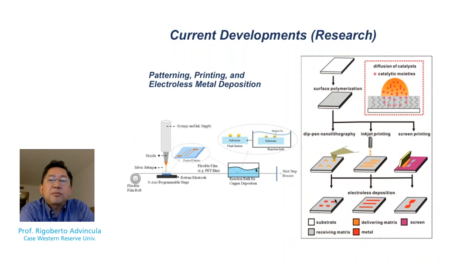Here, in a way, there's also a possibility of patterning, printing, and using, let's say, 3D printing to create areas by which you have surface functionalization capable of hosting what we call an electroless deposition. So in an electroless metal deposition, one can create or pattern the surface so that you have an attraction for the oxidized state of the metal. It could be a copper ion, nickel ion, platinum or gold ion. And then once you deposit them on the surface, one can activate them or reduce them or metallize them as part of the pattern. In other words, in electroless deposition, there is the possibility of using 3D printing to create the pattern. And again, as a final step, deposit a reduced metal on that pattern using an electroless deposition method.